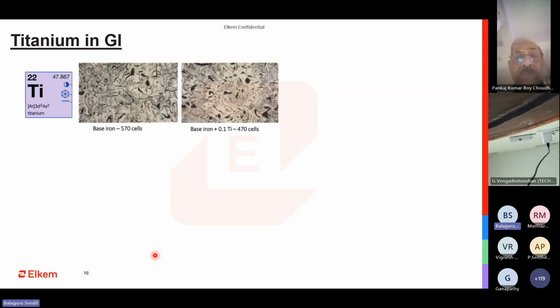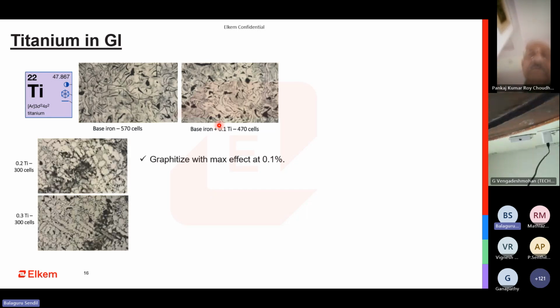So titanium, if I look at it, base iron at about 0.1% of titanium, which is not bad actually. It does a bit of refinement for gray iron microstructure. So I can say that it kind of graphitizes the matrix, maximum effect at 0.1%. But if I keep increasing it, 0.2, 0.3, because in the past, people have used titanium when they see that the casting surface finish, especially in gray iron, is not very great. After machining, they want to do a bit of refinement. It is still advisable to add some amount of titanium or chromium to achieve the matrix refinement, microstructure refinement, and graphite refinement as well. But that is about 0.1%.